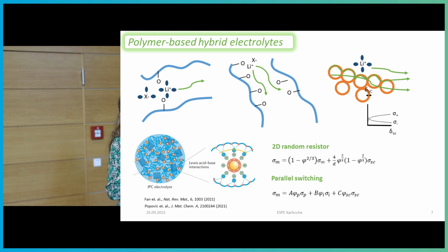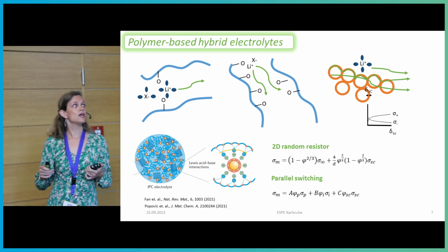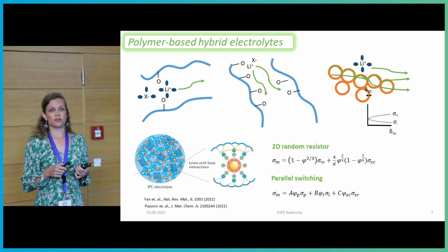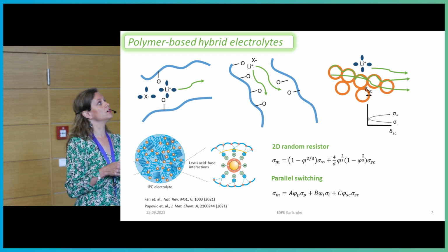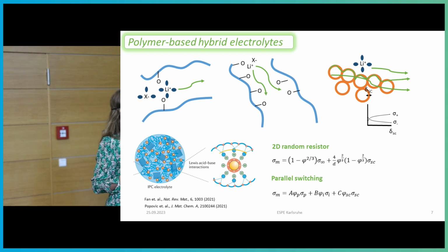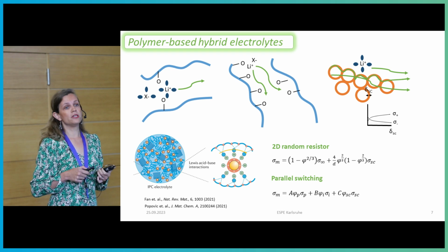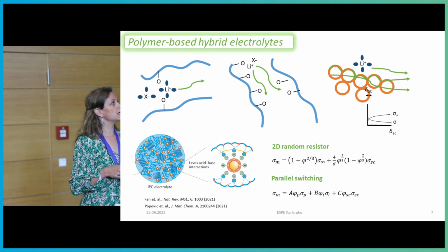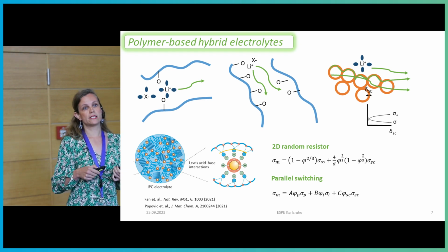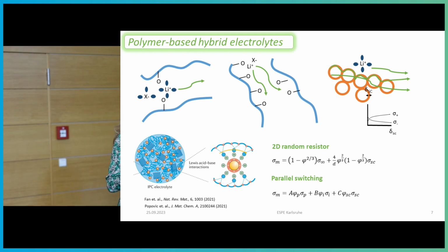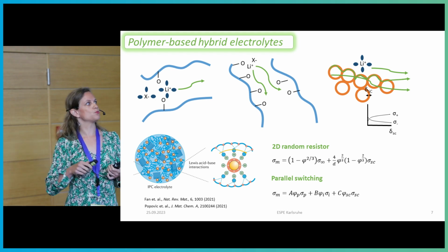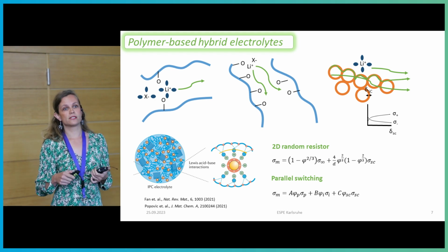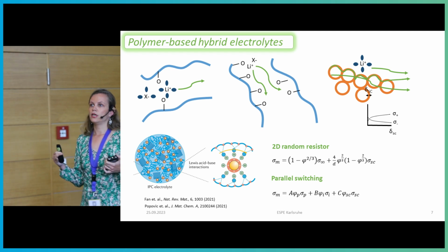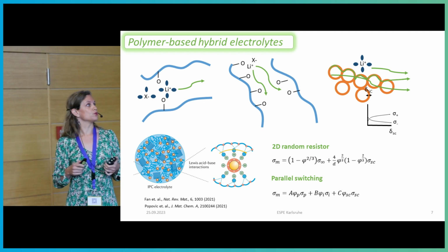So polymers might be either dry, where we have the movement of lithium ion on the chain, or they can contain a little bit of solvent, where we have this vehicular type of mechanism of movement. And once we start to add particles to it, first we amorphisize the polymer around those particles, but we might have also acid-base activity on the surface of the particles, where in the best of cases, we actually absorb the anion and immobilize it on the surface of those particles.